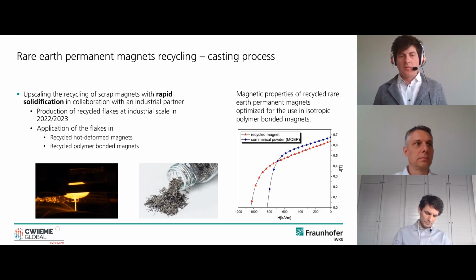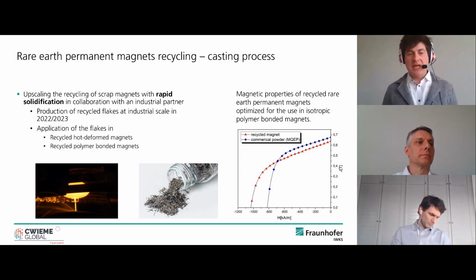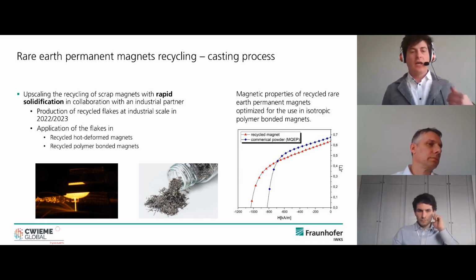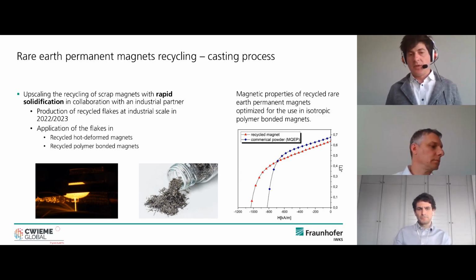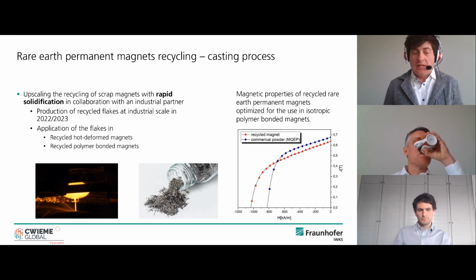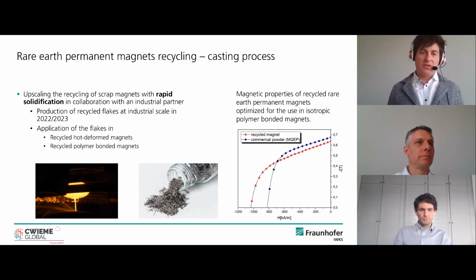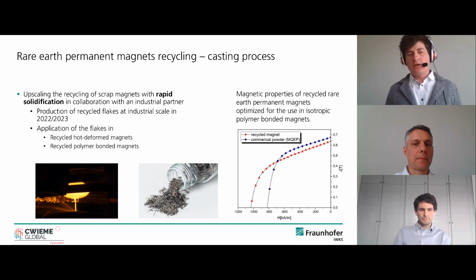solidification technique. So in this case, on the left-hand side, you see the melt spinning technique where we have really high solidification rates. The cooling is within tenths of seconds, and you get a material which is nanocrystalline. This material you can use for fully dense hot-deformed magnets, for instance. In Europe, more commonly, you produce polymer bonded magnets out of that. These magnets can be used in other kinds of small motors where you have high RPM, where you need small eddy currents, for instance.